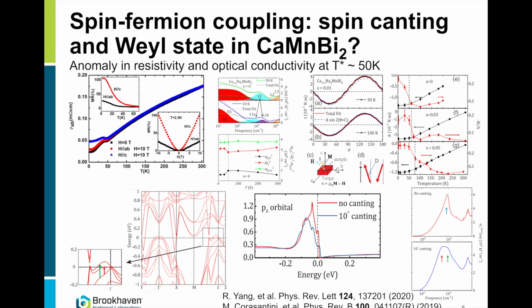And then again, the optical conductivity also showed some anomaly at the same temperature, indicative of Fermi surface reconstruction. Okay, fine, certainly Weyl. And of course, that's because of spin canting, because that's what you are looking for, as often. And so again, they did several bulk measurements here, torque magnetometry. Fortunately for us, the prediction from the torque magnetometry was that the canting is about 10 degrees. Now, 10 degrees is a credible canting. You do DFT calculations, and you indeed see substantial, measurable and consequential Fermi surface reconstruction.